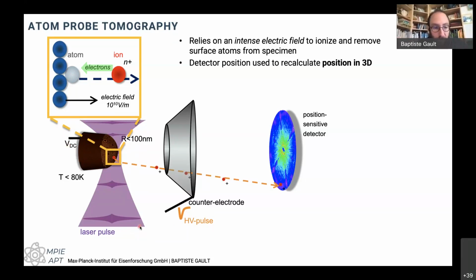Or I can just focus a laser tightly towards the end of the needle, and the needle is going to absorb some of the photons from the laser. Its temperature will increase for, depending on the specimen, sometimes just a few picoseconds, sometimes a bit longer. And this increase in temperature would actually assist with the field evaporation, which is a thermally assisted process. So the agitation of the surface atoms, the intensity of the field, at some point the atom can just be agitated enough that it just hops away, transitions into an ion, and then flies away.